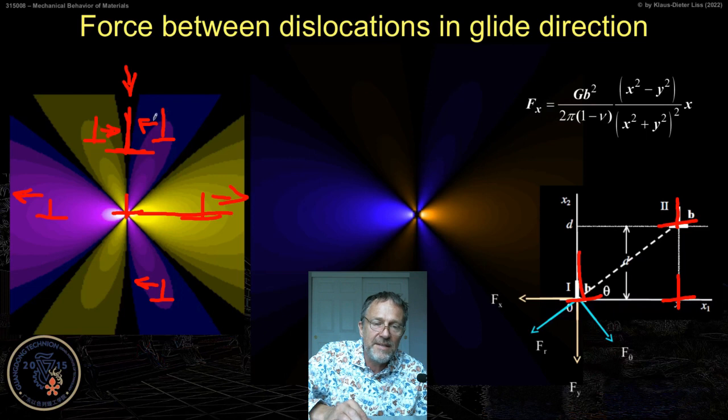So that's interesting. If I'm on the right side, it moves to the left if I'm in this quadrant, or octant, this triangle here. Then it moves to the left. And if I'm on the negative side of this triangle, it moves to the right until I go to the equilibrium position here just above x equals 0, and symmetric on the bottom, of course. So these are interesting locations.